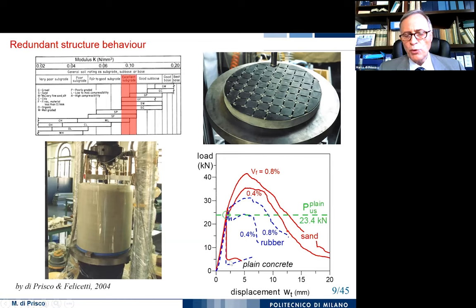And the same when we pass to a plate which is supported on different types of supports. Here we see the difference between a plain concrete, independently of the fact that we are on sand or on rubber. The rubber is in blue, the sand is in red. But when we have the continuous support of a rubber over a sand, you can see that the response changes completely. So what is important to understand is that if we increase the redundancy of the structure, we can see immediately a very good behavior in terms of bending,